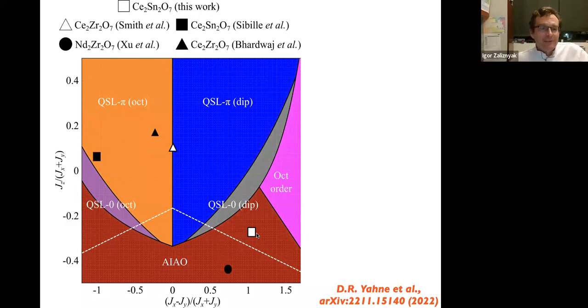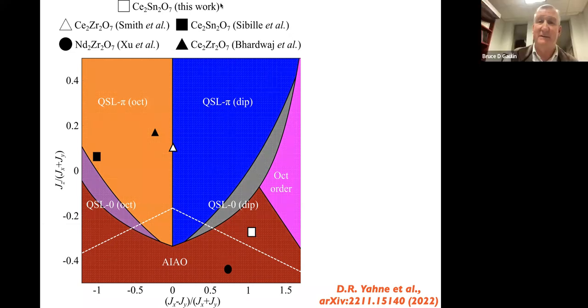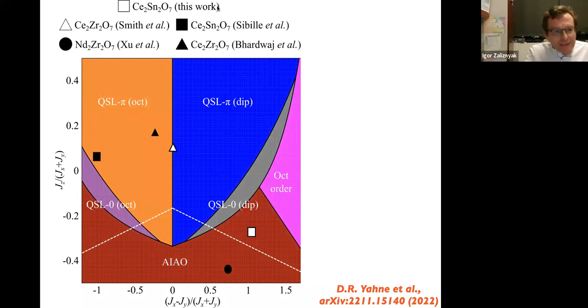However, if your effective spin is made of plus minus 3/2, S plus doesn't connect the two states, and so you cannot see any spin wave. That's full stop. That's why I was asking about the anisotropy of the G factor. You can only see spin waves to the degree you have Gx, the transverse G factor. But if the ground doublet of plus minus 3/2 is protected by symmetry, then the intensity of any spin wave will be exactly 0. And by the way, that leads me to my second question or a remark.